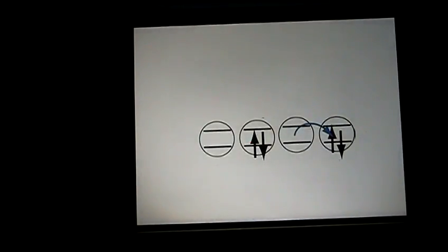So the point is, this electron that is highly excited, I don't want it to die into phonons, which takes 10 to the minus 12 seconds. In the meantime, is it possible through mechanisms like that to allow the death into some form of death that I like? Why do I like this form of death? Because I have now twice the current. I have 4 carriers, two doubly occupied sites and 2 electrons, which through this voltage that I create across the interface, I can collect through the leads.